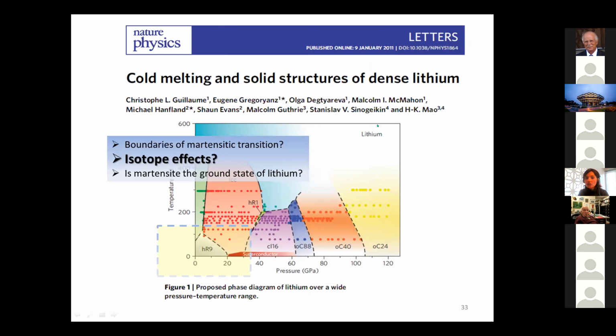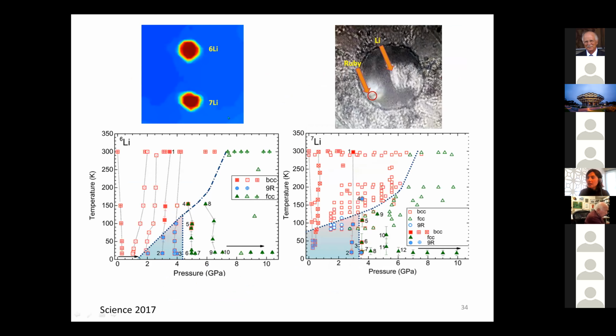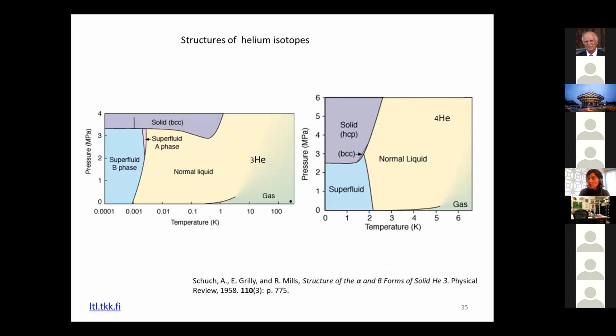And the question that was remaining was, okay, let's look at the isotope effect. Is that showing the same thing? I don't want to make it a long story. We did again side-by-side measurements, and we saw, wow, lithium 6 and 7 have different boundaries. The boundaries of this blue region, which is Martensite, differ from each other, shifted from each other. And it solidifies the idea that nothing else that we know, other than isotopes of helium, shows differences in boundaries of their solid phases, as far as we know. This is a very old study, so it has to be revisited, in my view.